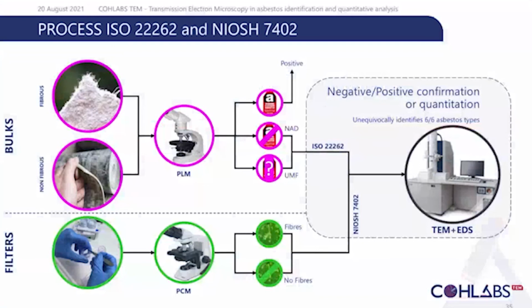For filters, we are using PCM first. There are 2 reasons for that. One main reason is that we need to have PCM counts if we find some fibers using PCM. And if no fibers are detected, we're going to ask for confirmation. So for either outcome, we then prepare the sample using the NIOSH 7402, and we're going to go through a TEM and EDS analysis as well, for quantitation this time, and unequivocal identification as well.